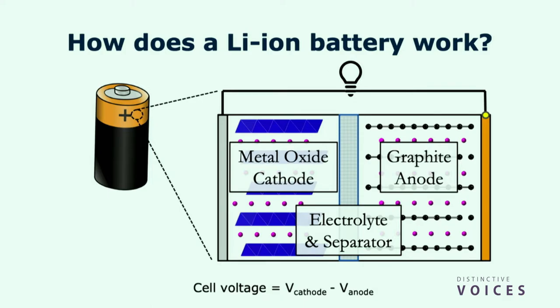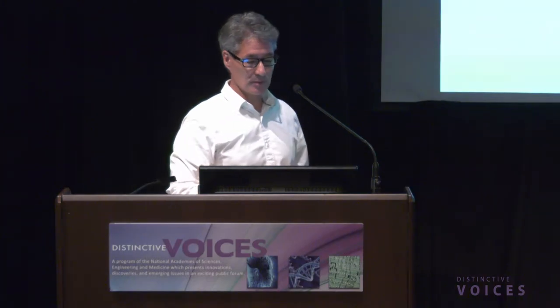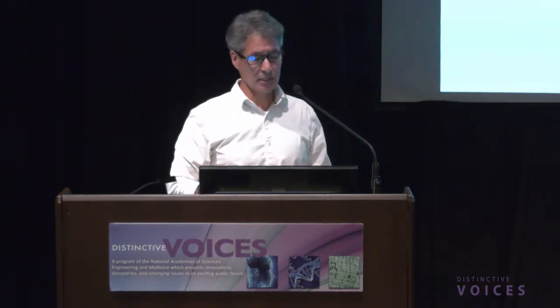And then it's important to note that in an electrochemical cell, you want to maximize the voltage of the cathode and minimize the voltage of the anode, as close to zero as possible, because the difference between those two gives your cell voltage. And you want to maximize the cell voltage to maximize power and energy.